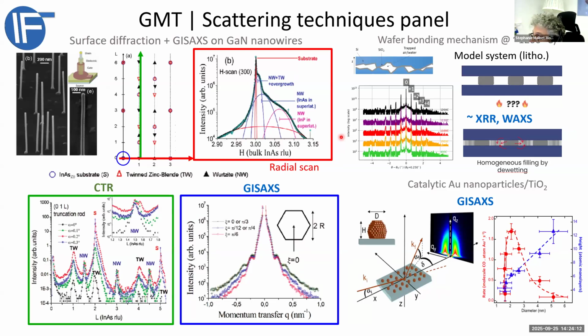In this instrument, as I said, we are able to do a lot of kinds of experiments. As I said, GISAXS there, and then this is a crystal truncation rod. So imagine you have this reciprocal space of your sample, and you can probe it. There are two possibilities. If you are rich and you have a fast detector and a lot of flux, you could do a reciprocal space map and cover any points in the reciprocal space with some scattering intensity. So it takes time, and you need to have some flux in your source. So it's sometimes better to go faster, just to make some radial scan or a specific scan. This is a crystal truncation rod scan, in order to rapidly have the distance between the nodes, and to locate the node with respect to the space origin.